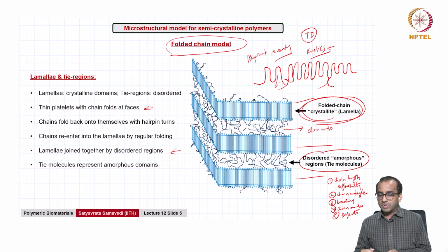Of course, the kinetic component again, which simply has to do with, at that operating temperature in the melt, for example, what is the probability that these chains can come together and crystallize. So, all of that will be affected by these factors, and that in turn can help explain why many of the polymers or most polymers that we see can never be extremely crystalline, right. We can talk about 40%, 50%, 70% crystallinity, but achieving 100% crystalline polymers is only possible in the ideal case in theory.